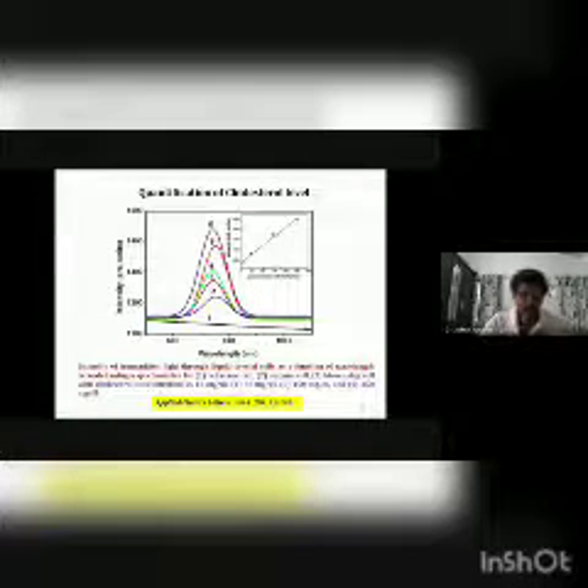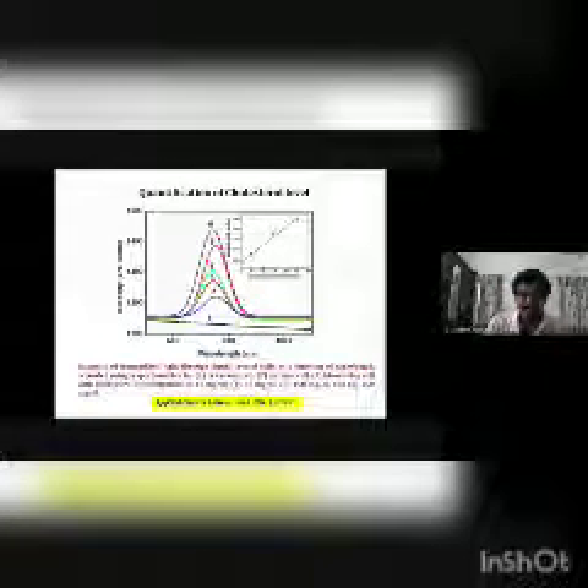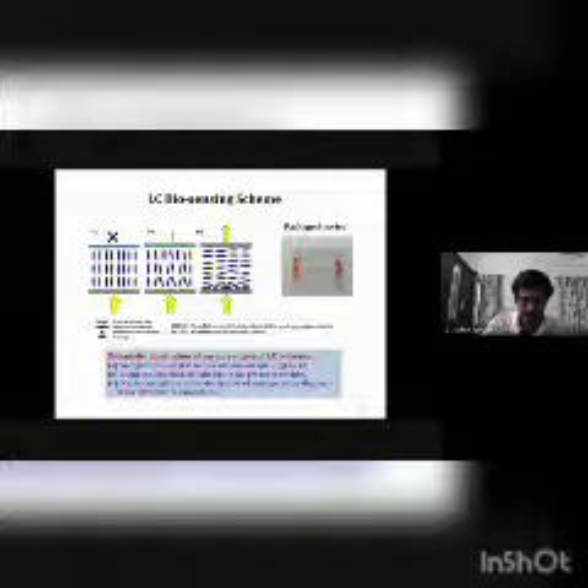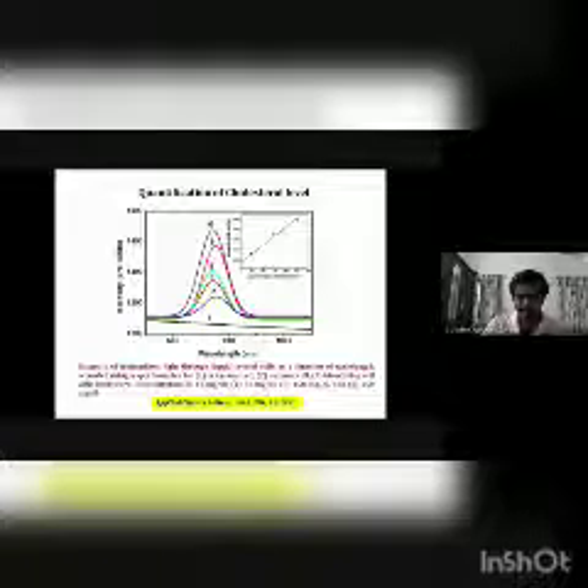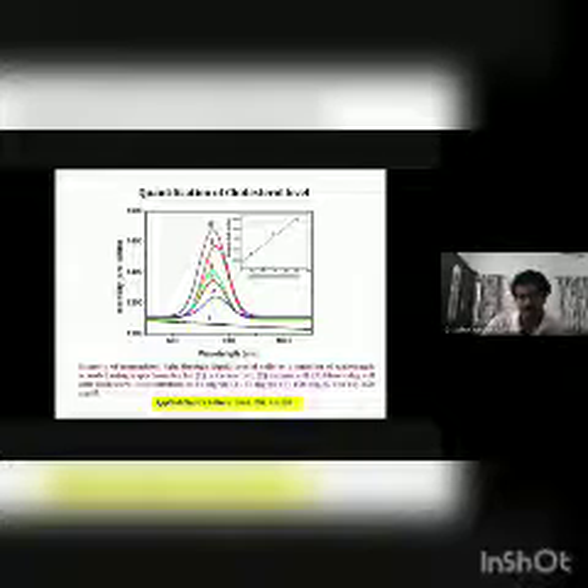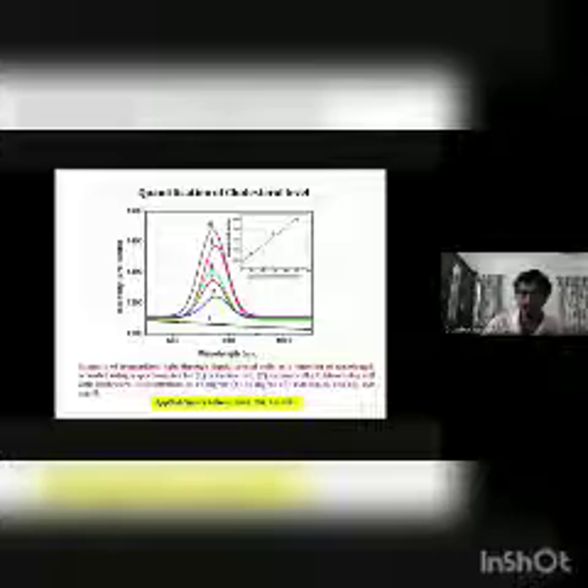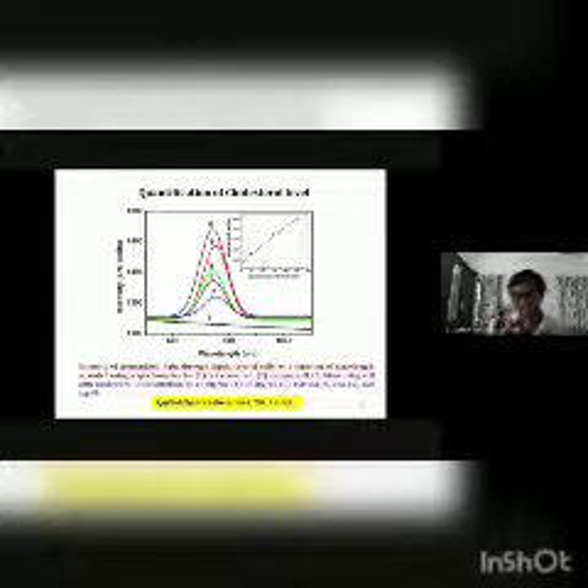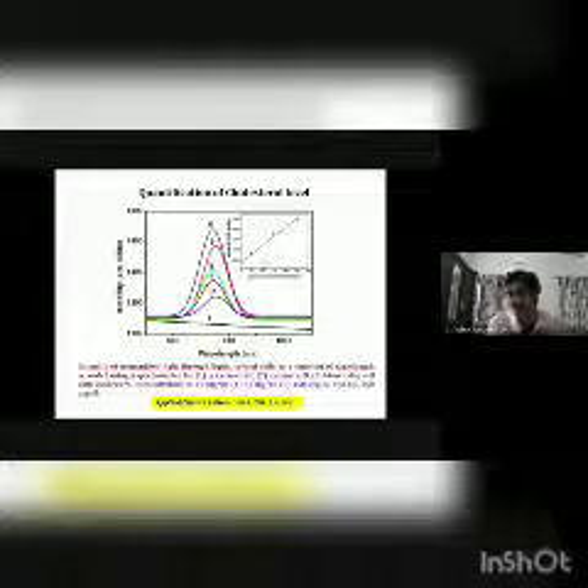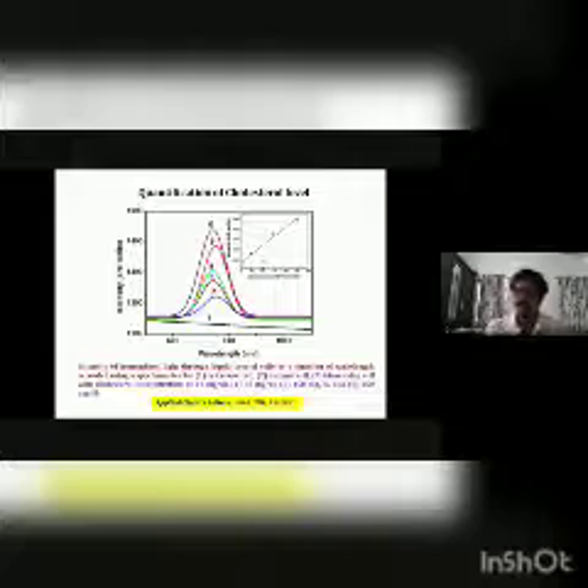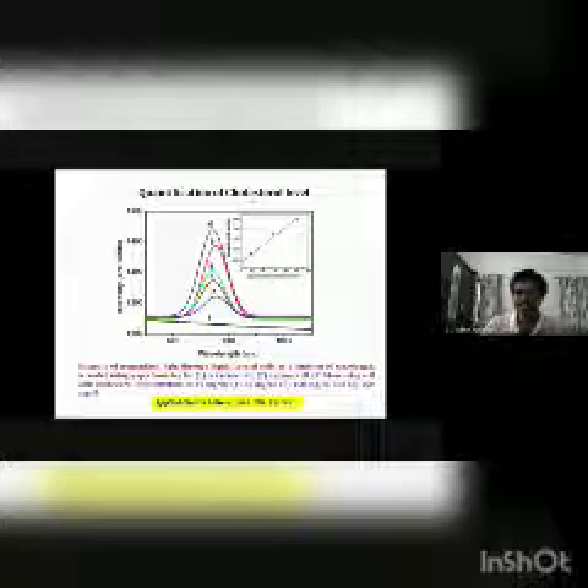And here we have quantified the light passing through this by using a spectrometer, and we found that the intensity of light is getting higher with the concentration of cholesterol. It's a linear thing. So if you have an unknown sample where you don't know the concentration of this molecule, you can just find the intensity of light passing, and you can correspond those intensities.